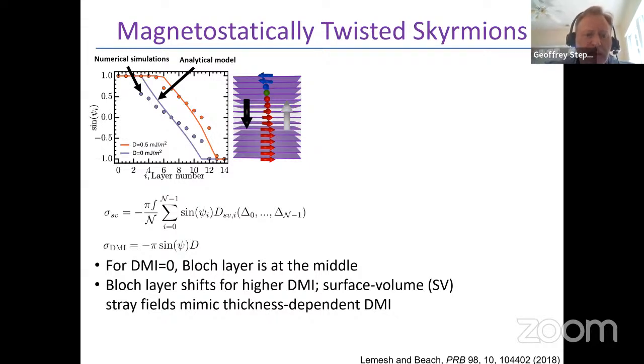But the stray field interaction itself turns out to look exactly like an effective DMI, and that effective DMI applies layer by layer by summing up the stray fields from all of the other layers. And it can either add to or subtract from a DMI that is induced at interfaces in these materials. So this node can be pushed through the film, but that gives a few consequences. It takes a much higher DMI in a multilayer to get a fully Néel structure. But also, at that node in the middle, the stray-field-like interaction is exactly balanced by the DMI.